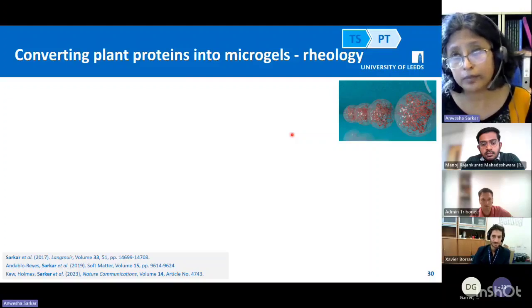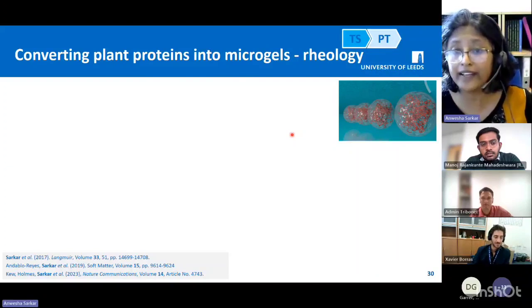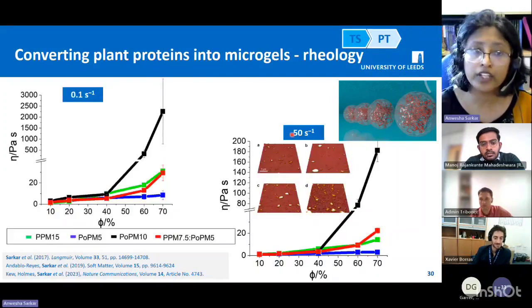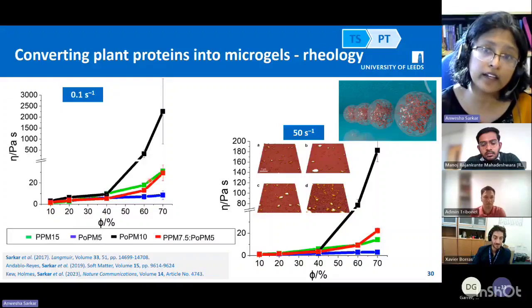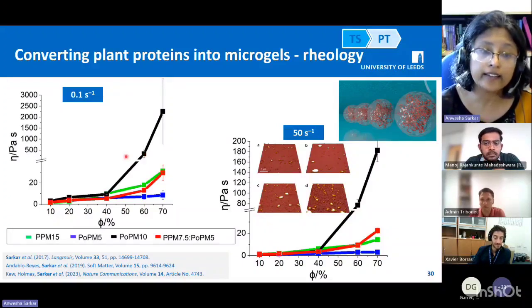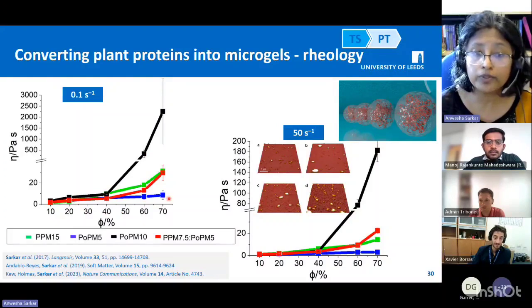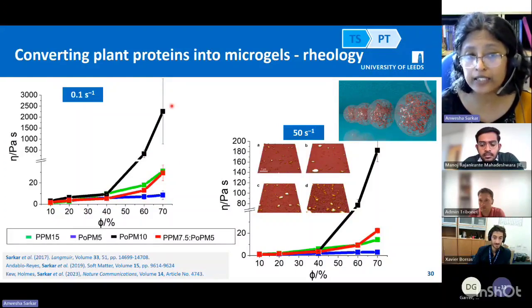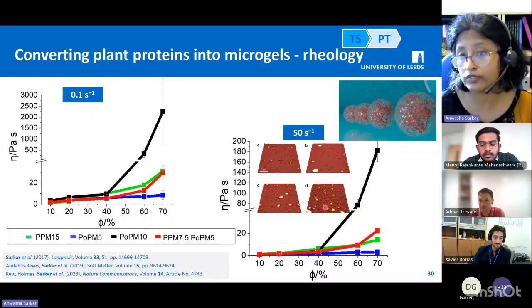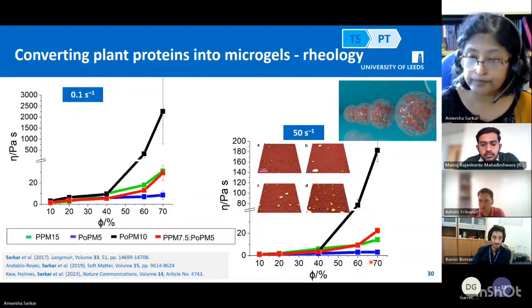So what we observed is that our hypothesis was simple: if you convert the plant protein into a microgel, you can actually increase the lubricity. So here what we can see in the rheology data is that the rheology of plant proteins changes dramatically if you make it into a microgel. It increases quite massively. So you have an order of magnitude increase if you increase the volume fraction of the microgels.